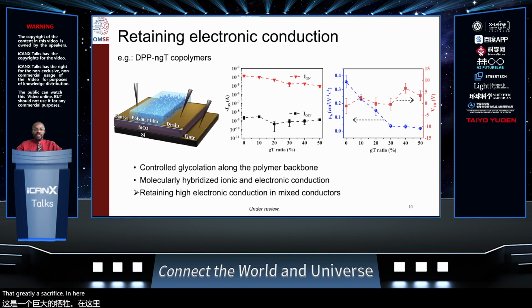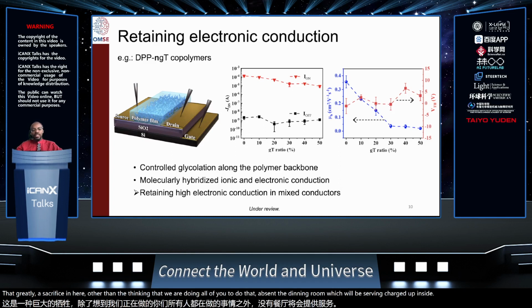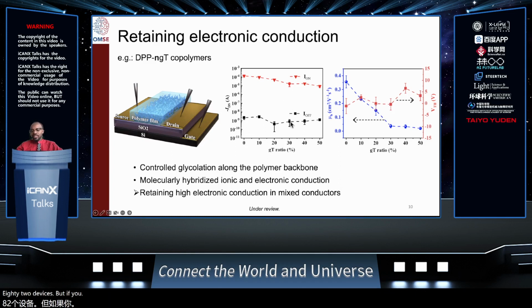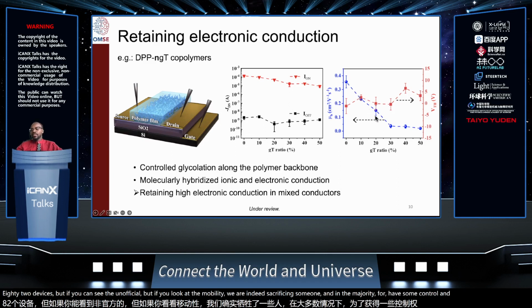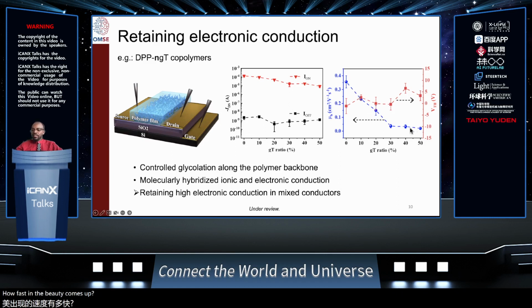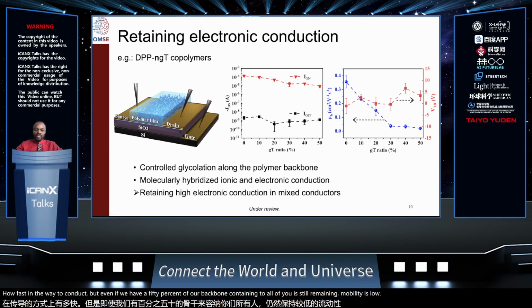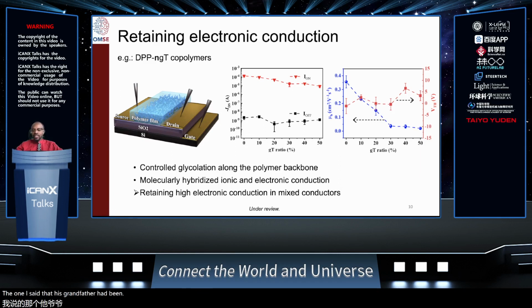Here, the thinking is that we're adding polar groups, so these are oxygen-containing groups, which will be serving as charge trapping sites in FET devices. But as you can see, the on-off ratio is conserved. As you look at the mobility, we are indeed sacrificing some of the mobility, but we have some control in terms of how fast the mobility can drop. Even if we have 50% of our backbone containing these polar groups, we're still retaining mobilities as high as 0.01 centimeters squared per volt second. In this class of material, this is not poor conduction given how many polar groups we are adding.